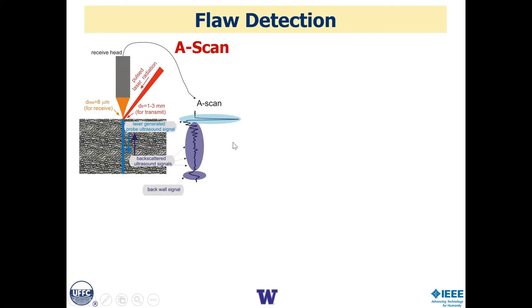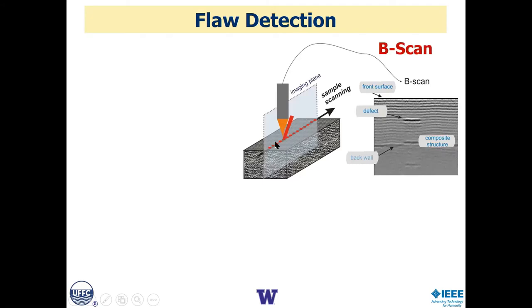If we now optically scan the source and detection beams very, very rapidly along the line, we can get a cross-sectional image such as this of one of these laminated composite materials, showing the basic structure as well as some defects. What I'll show you subsequently is that we spatially filter these raw images to remove the periodic structure and just look for flaws. So you see images which look very clean other than where there are flaws.